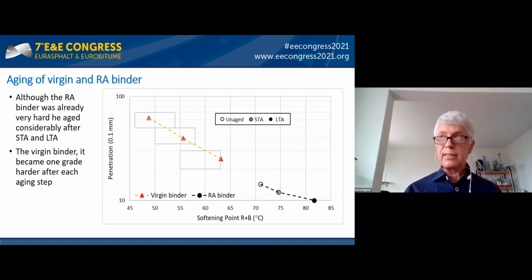So then, to assess the results of these binder blends, we have to compare it to something because we don't have any requirements to meet. So we used the virgin binder we also had as additional binder, which we did age in the same way, short-term aging and long-term aging. And you see we come from the penetration of about 60 down to 25 penetration value. It's still quite far away from the reclaimed asphalt binder penetration, which is about 15. But this was actually not the goal to reach that.